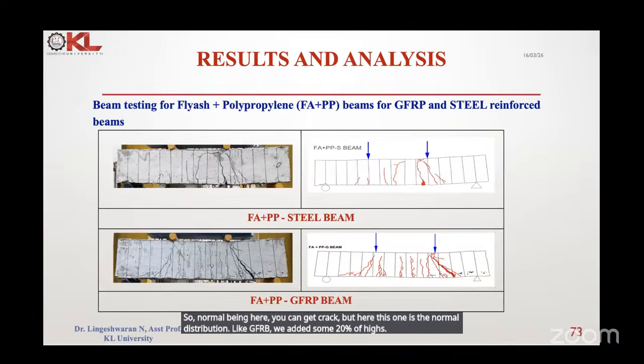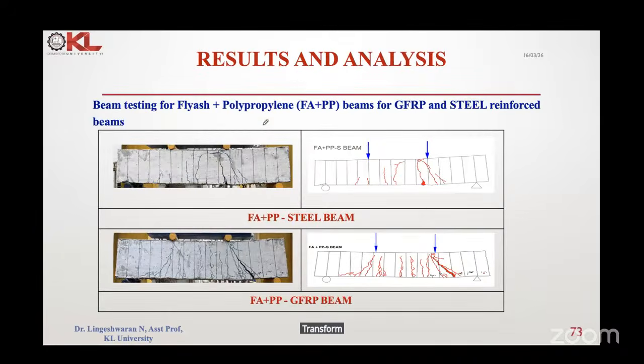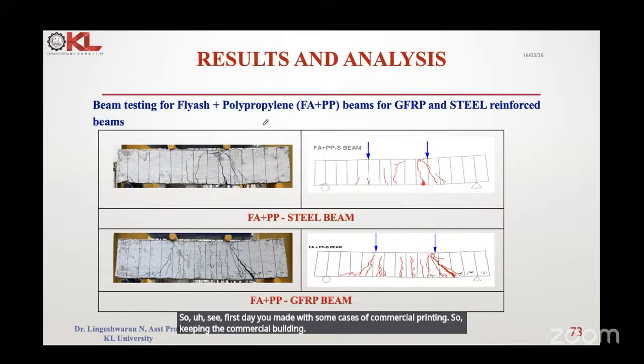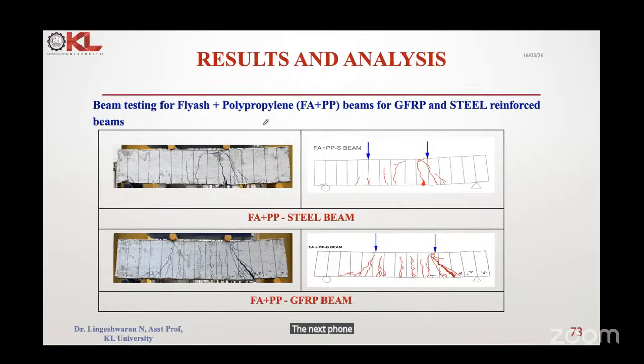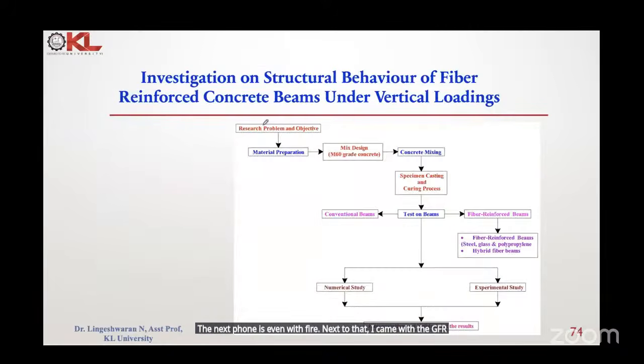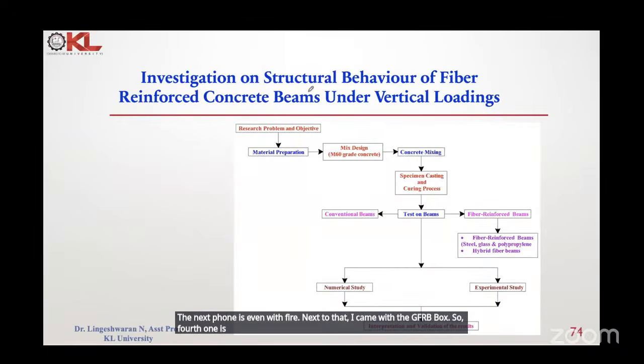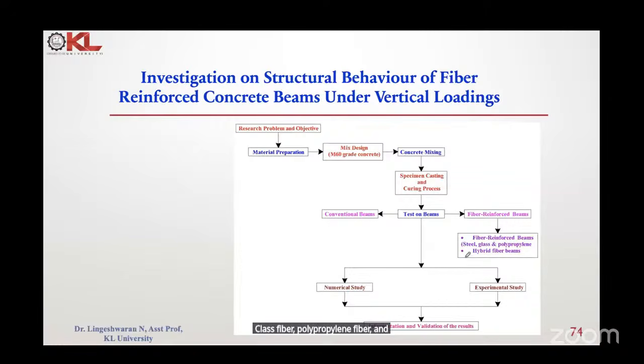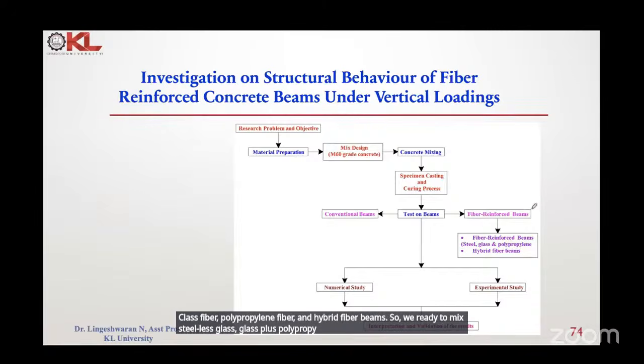So you can see here, this is the beam testing for fly ash plus polypropylene beams with the GFRP and the steel reinforced beams. Next, first I made one case study of a commercial building. Keeping that commercial building, I went with recycled aggregate. Then I went with fibers. Next I came with the GFRP parts. The fourth one is we tried to work on fiber reinforced concrete beams under vertical loading. Here we went with different types of fibers like steel fiber, glass fiber, polypropylene fiber, and hybrid fiber beams. We mixed steel plus glass plus polypropylene, so that one we tried.